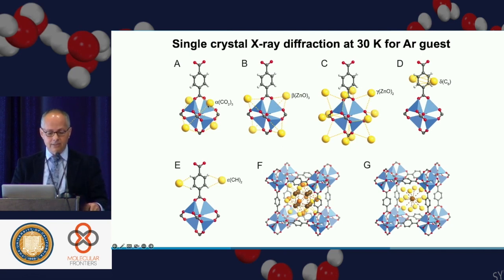Argon is in yellow, and it turns out that everything you look at in the metal oxide unit is actually an adsorptive site. All of these bind argon, as well as the six-membered rings and the edges of the six-membered rings. So that's where every atom in the structure is an adsorptive site. You're making maximal use of your material, and that's why they have extremely high surface area. The more adsorptive sites you have, the higher the surface area, because the surface area is coming from the amount of nitrogen that you have measured in the gas adsorption isotherm.